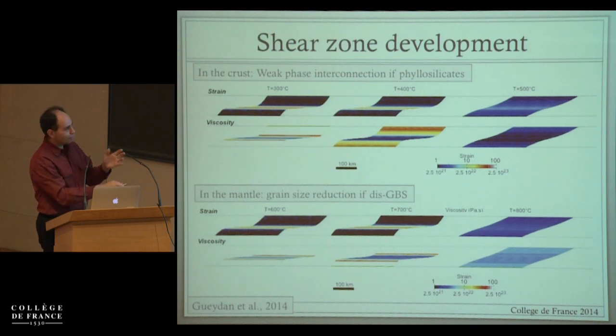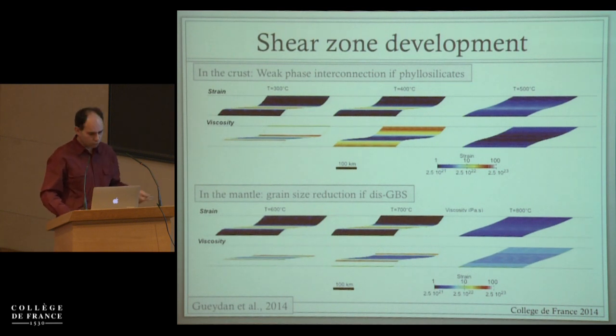And the fun thing that we noticed is that in both cases, and it didn't have to happen like this, you form shear zones when you're at relatively low temperature and you don't when you're at higher temperature. The reason being that the phyllosilicates break down, and actually their strength is about the same as the surrounding rocks eventually, so you don't have much contrast in strength between the phases, so you don't really have a weak mineral anymore. And here simply because when you are at high enough temperature, the way the deformation regime works, you avoid this magical regime of GBS, and we can understand why it doesn't do this. Again, I don't have much time to present the details, but that's still our conclusion.